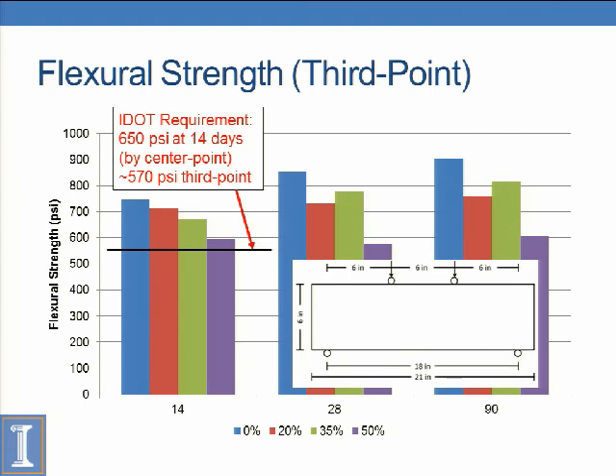Now that is for center point loading. What we did is called third points. You're loaded at every 1/3 the span. So you have 4 points essentially. 1, 2, 3, and 4. For center point, you remove one of these top ones and put it in the middle. Center point will have a higher flexural strength, but higher variability as well. This setup, you'll have a constant moment in between the span where it'll fracture. So that's why we did third point testing instead.